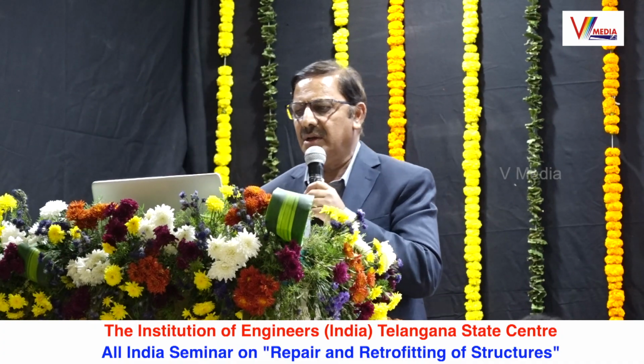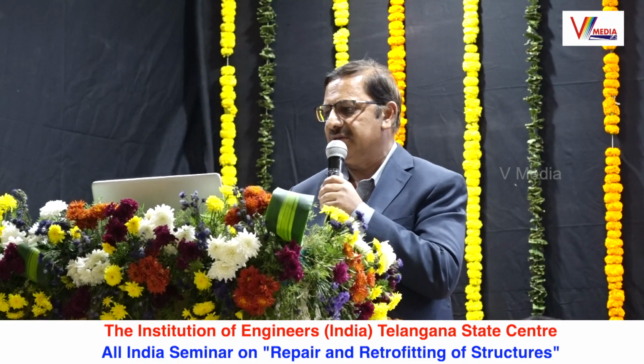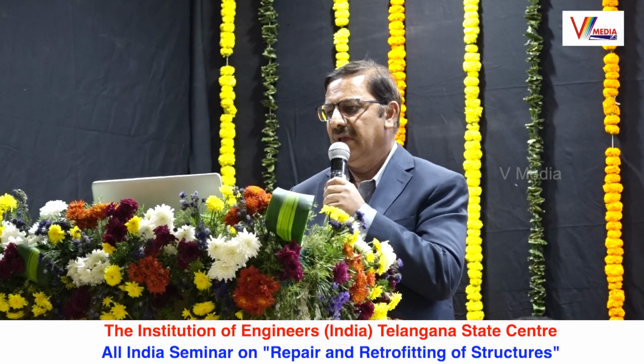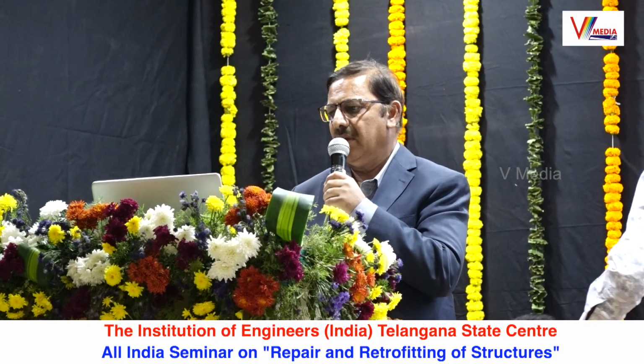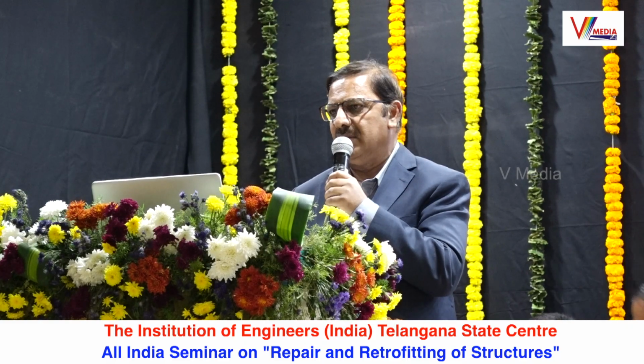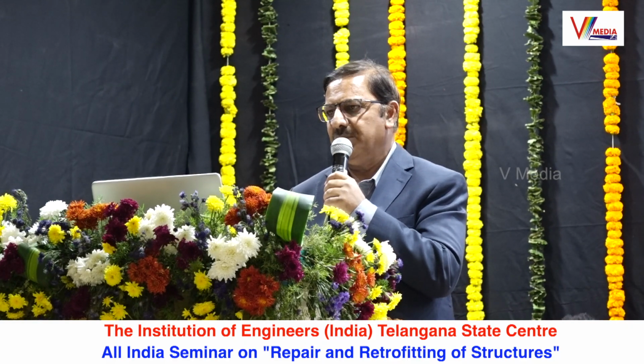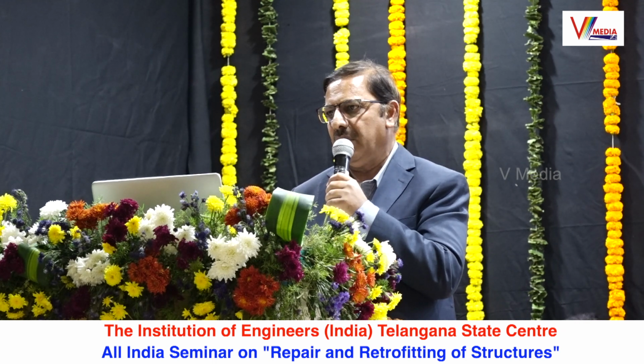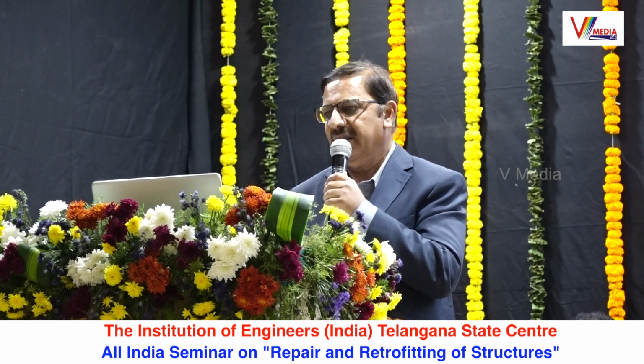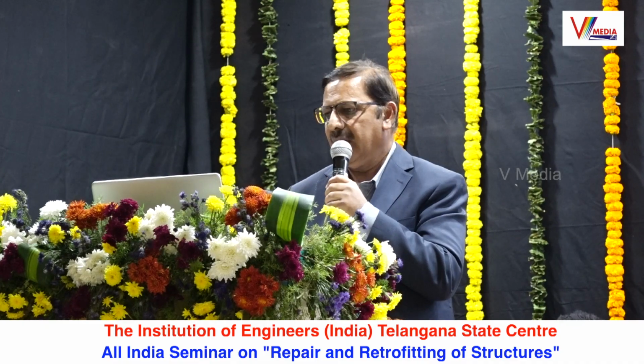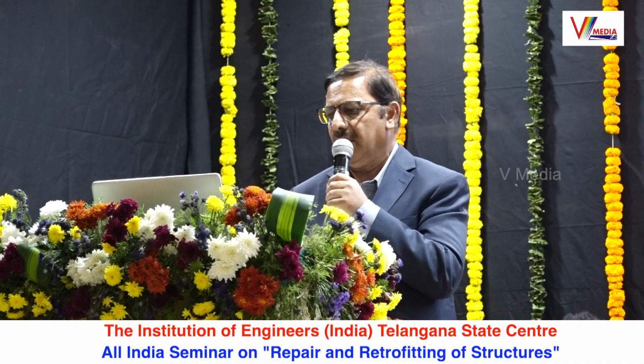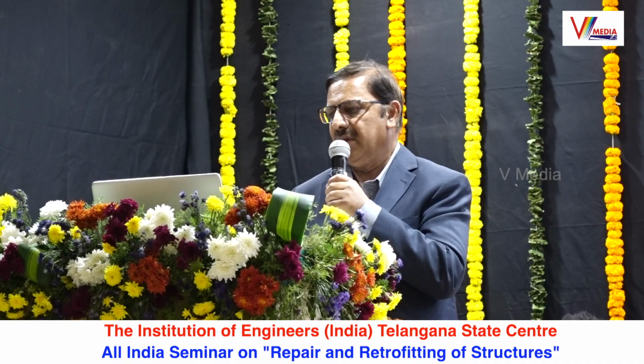So as a conclusion, design of durable concrete structures in harsh exposure conditions is a two-step process. One, good quality control, quality concrete, no compromise for that: low water cement ratio, use of supplementary cementing materials, larger cover, good curing, and good construction practice. And then additional protection. You need additional protection, and additional protection can be surface coating, epoxy coated rebars, stainless steel, or cathodic protection.